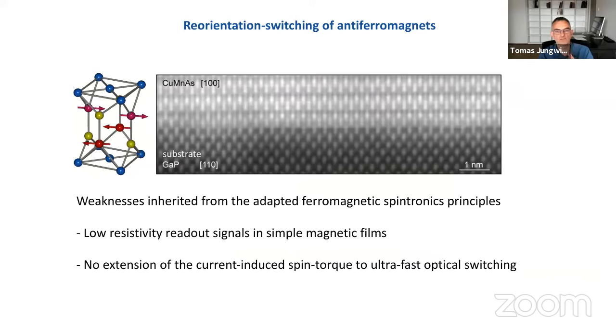So that brings me to the wrap up of what we've learned so far about the reorientation type of switching of antiferromagnetic systems based on these simple single layer film antiferromagnets. We can explore some intriguing topological variants of these phenomena and features. But we also saw that we inherited some weaknesses from the ferromagnetic spintronics principles that we adapted to antiferromagnets. One of the weaknesses was that we see these low resistivity readout signals in simple magnetic films, and also that there is no obvious extension of the current-induced spin torque mechanisms of switching towards the ultra-fast optical switching by the single femtosecond laser pulses.